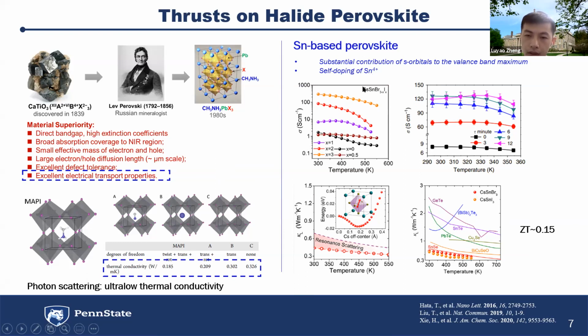And also, although on this side is the cesium rather than the organic cation, the organic cation has more freedom for motion and probably will lead to more phonon scattering effect. But the cesium is here, it still has certain freedom to move inside of the cage. So they still can give us scattering of phonons, leading to a low lattice thermal conductivity. And compared with other typical thermoelectric materials shown here, it is pretty low. This is good for obtaining a good ZT value.